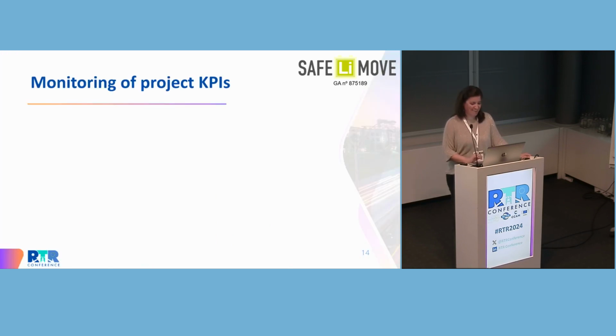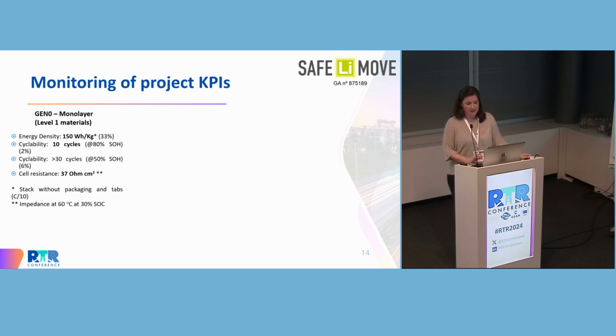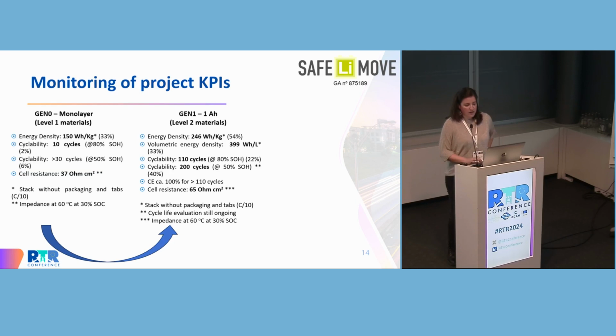2 minutes, okay. So, monitoring the KPIs. Here, I wanted to compare. I think it's nice to see how the technology has evolved along these 4 years. So we have the Gen 0 monolayer, where we have energy density of 150 watt-hour per kg. So if we compare to the target that we defined, we were around 30%. Then with Gen 1 1 ampere hour cells, we were able to push this value up to 246 watt-hour per kg. As well, we were able to improve the cyclability of the cell compared to the Gen 0 cells.